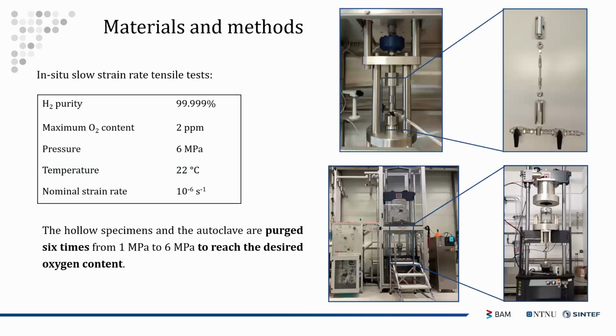So, considering the testing techniques both in the autoclave and with hollow specimen, we use the same hydrogen purity, which is grade 5 hydrogen. And we try to obtain a very low oxygen content because oxygen is well known to be an inhibitor for hydrogen embrittlement. So we purged 6 times from 10 bars to 60 bars in order to achieve the desired oxygen content within the autoclave and within the hole of the hollow specimen.